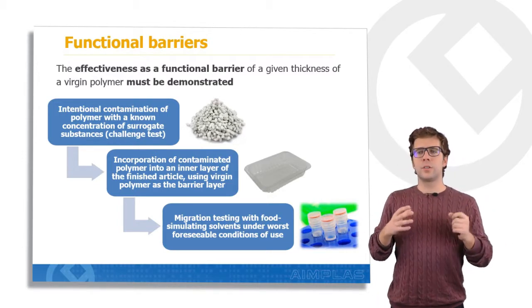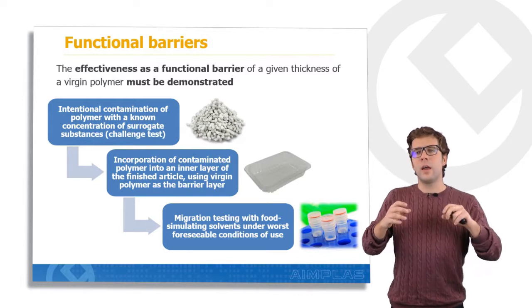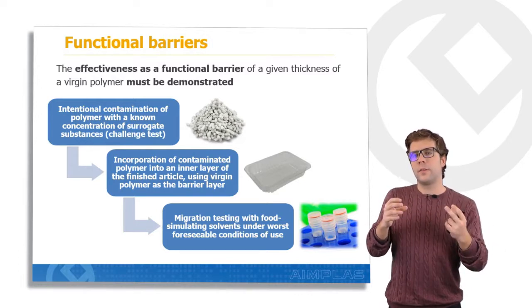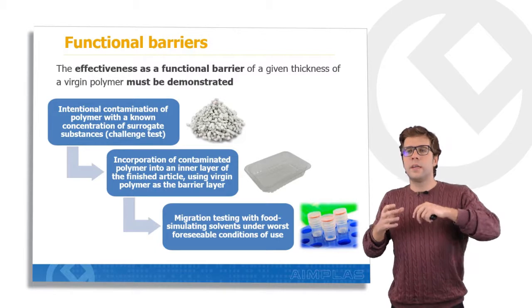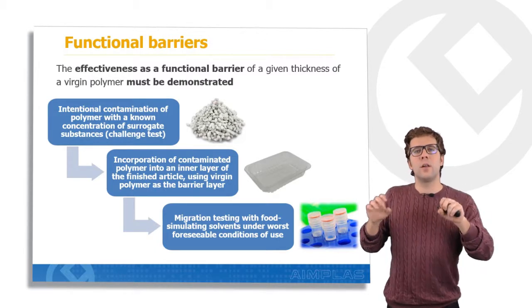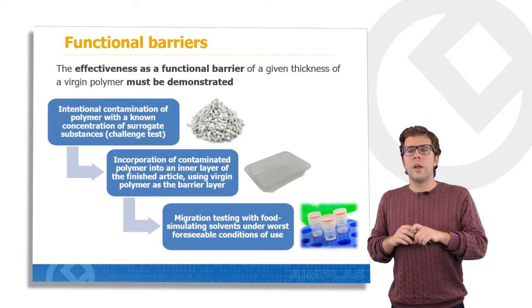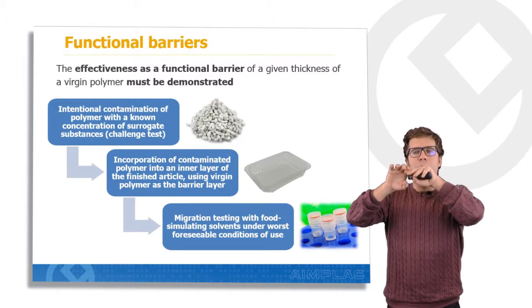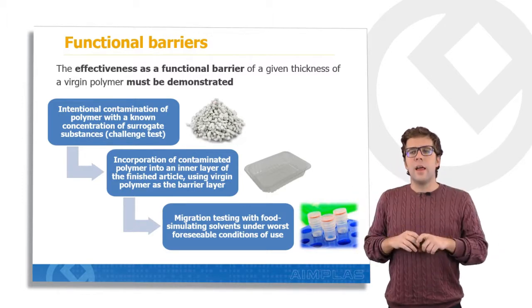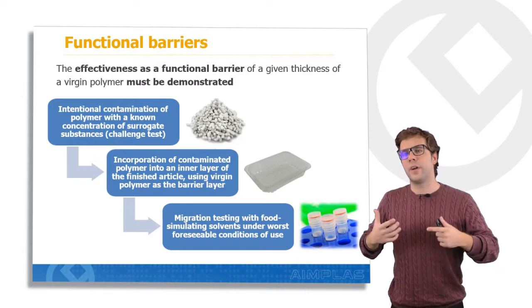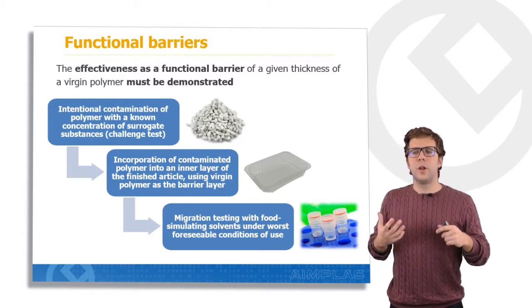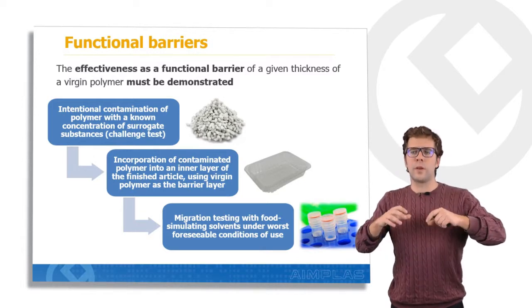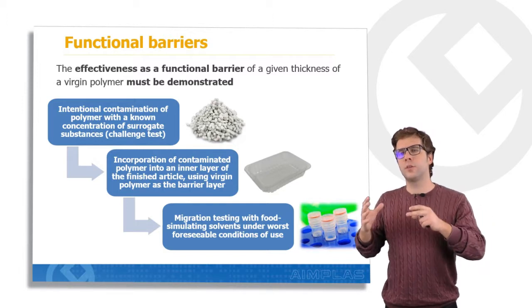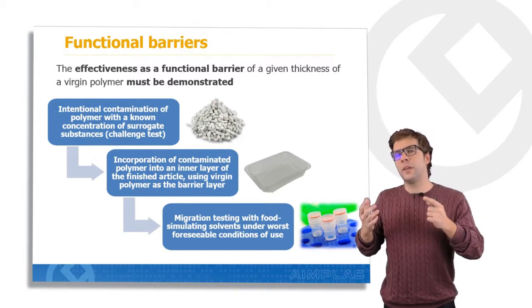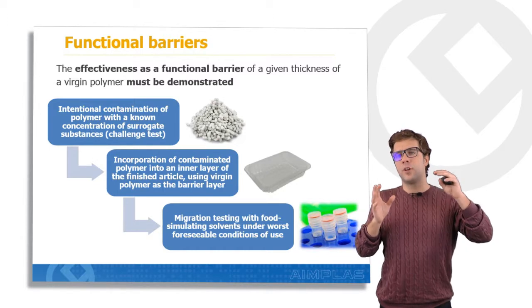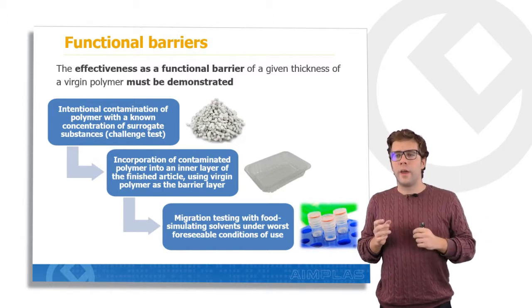Then we use this contaminated polymer and incorporate it into the inner layer of the finished article of a multi-layer structure, using virgin polymer as the functional barrier layer. And finally, we perform migration tests with food contact simulating solvents under the worst foreseeable conditions of use, and we determine the migration that is produced through the simulants.